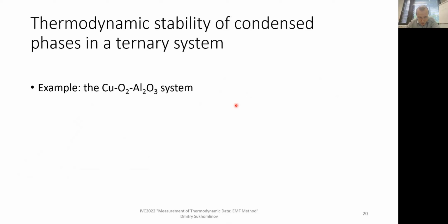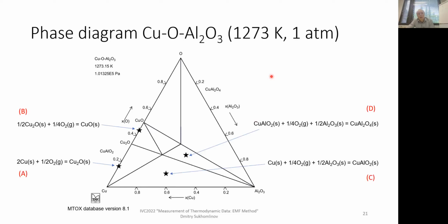Another example, more complex, a ternary system. Copper, oxygen, alumina. So we want to determine the Gibbs energy of formation of all, well, let's say most of the condensed phases, solid phases in this system. That's how this system looks at 1 atmosphere pressure and 1000 degrees C. And we need to know equilibrium oxygen partial pressures in different sides of this diagram. So they are marked with stars.